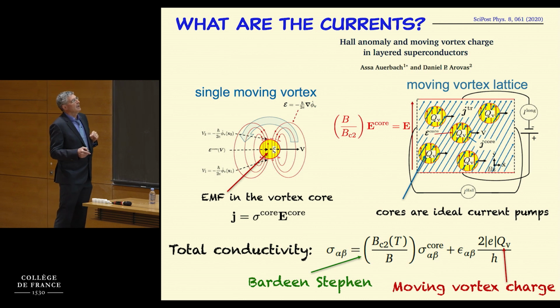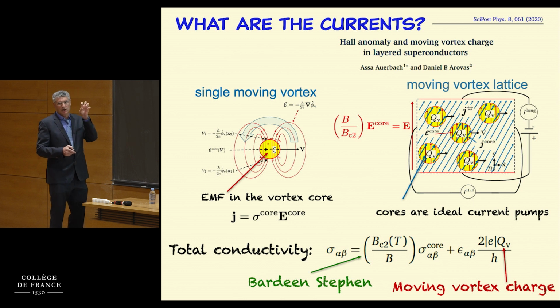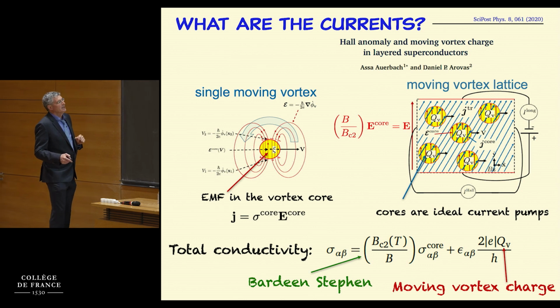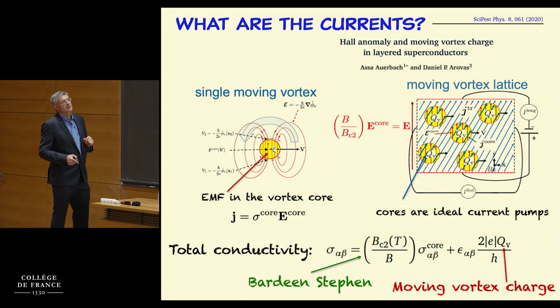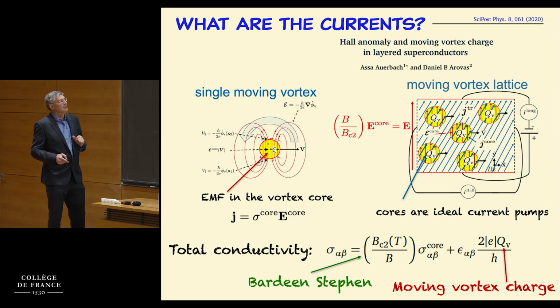But there could be another contribution. What is that contribution? Let's imagine that each vortex attracts some charge to it. Notice the vortices are moving perpendicular to the electric field, so that will be a Hall coefficient, Hall conductivity. And it's given in a very nice and simple way. It's the Cooper charge 2e times the charge attached to the vortex divided by h. So it's an expression like e squared over h you get in the quantum Hall effect. And that expression here is the reason you can get a Hall sign reversal. Because if this Q is different sign than this sigma of the normal state, if this becomes larger than that, you get a Hall sign change.